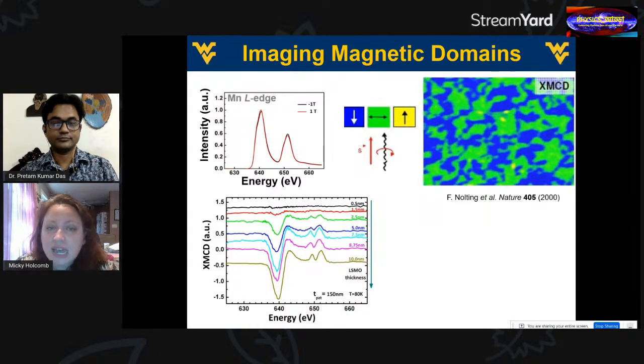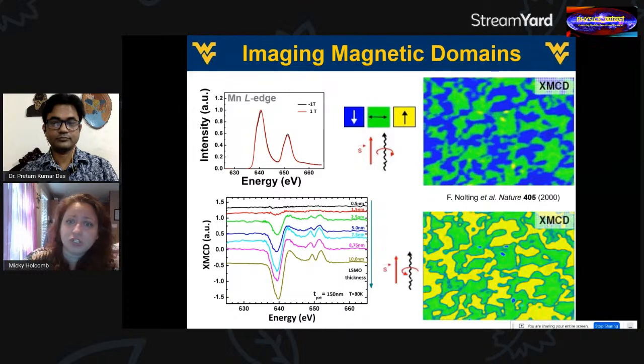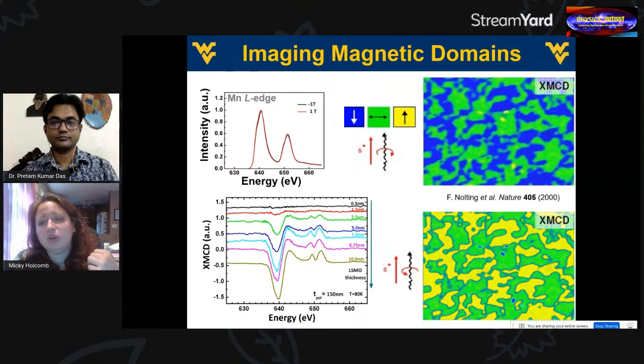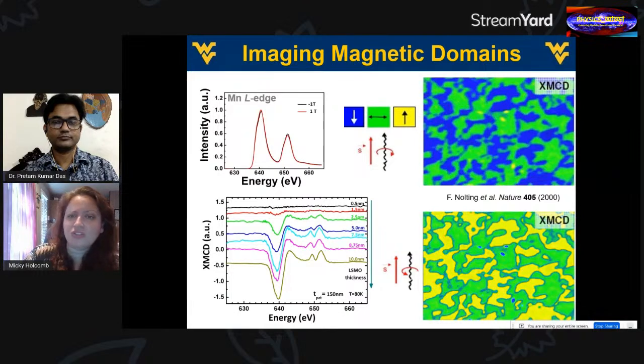And so you're going to get slightly different intensity depending on whether the magnetic domain is aligned parallel, anti-parallel, or even perpendicular to the polarization of your light. And if you want to verify that this is actually a magnetic effect and you don't just have some roughness effect, what you can do is you can either switch the polarization of the light, which is what we do a lot, so it should reverse if this is the effect, or you can also do things with switching the magnetic field too. This is also common.